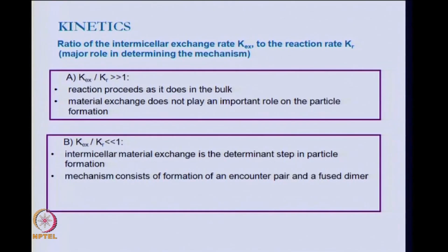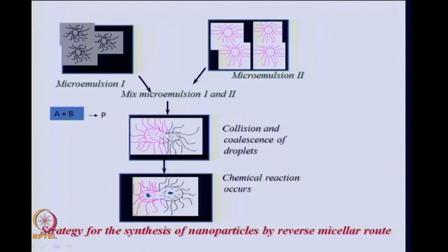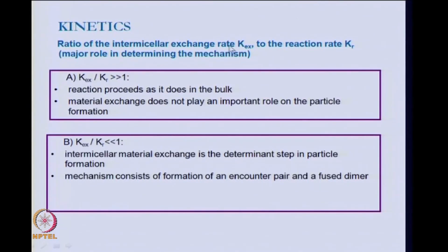Now, the kinetics of these intermicellar exchange. This is the step where you are having the intermicellar exchange, and the kinetics of the intermicellar exchange rate compared to the overall or bulk reaction rate is very important in determining the mechanism. Now, if the exchange rate is very high compared to the bulk reaction rate, then the exchange does not have any particular role to play on the particle formation.